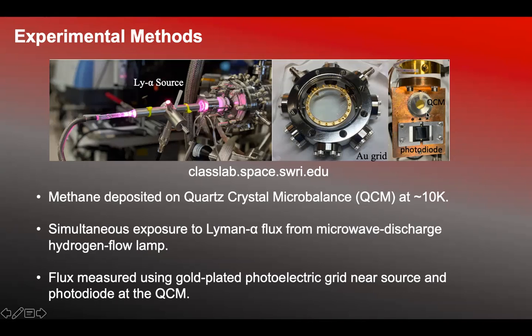So within the chamber, there is what's called a QCM. QCM stands for quartz crystal microbalance. And that quartz crystal microbalance is a small quartz crystal set that vibrates at a certain frequency and can be measured, of course, to a very good precision. And as the methane deposits on that, the frequency starts to slow down. It becomes a much lower frequency. And therefore you can go through the calculations and calculate how much mass has been deposited on that crystal based off of the change in that oscillation.